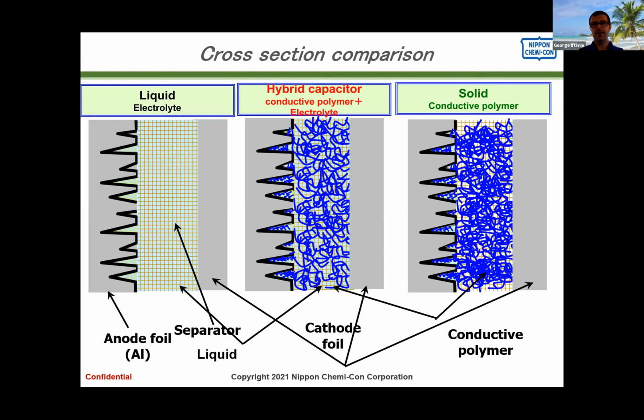On the EDL caps or supercapacitors, the construction is basically the same. The difference is the electrolyte is different, and we use what you call a PC electrolyte, propylene carbonate electrolyte. We don't use acetonitrile electrolyte for our supercapacitors. Acetonitrile has a very low boiling point and flash point. And then the second part is when it does combust or vent, it has a tendency to create cyanide, especially when it burns. So we use PC, what we call PC electrolyte, which has a slightly higher ESR, especially at low temperatures.